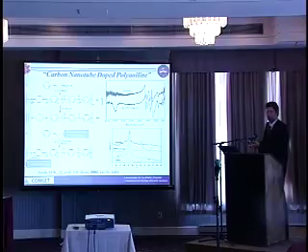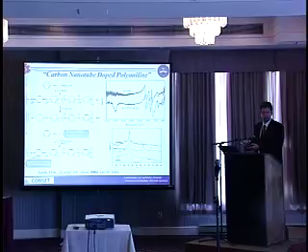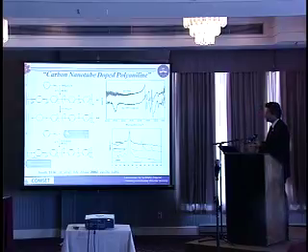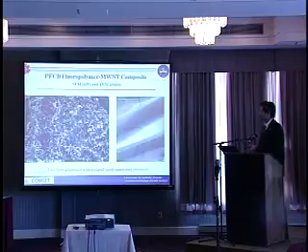So this is carbon nanotube doped polyaniline. You can get conductivities of polyaniline with very, very little doping of carbon nanotubes, 100-fold increases in conductivity. And this is clearly doped reactions by the defect areas or whatever. But that's something I want you to keep in mind, is these nanoparticles, nanomaterials that we're using are actually reactive, and we can do a lot of chemistry with them.